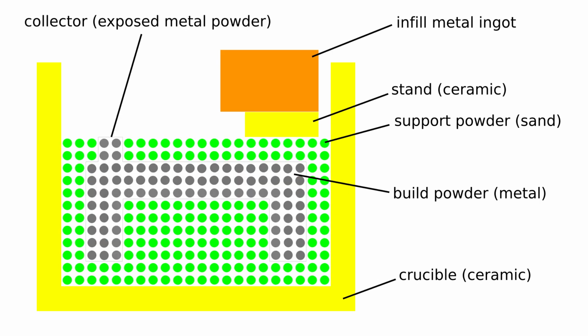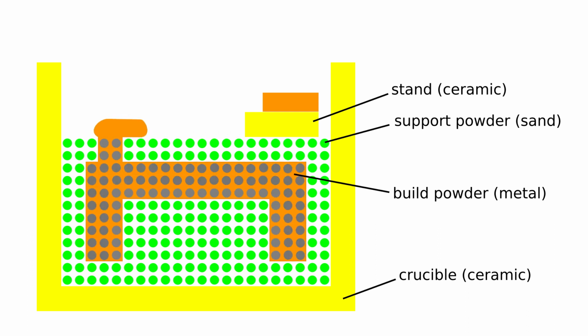In the Puddle+Stand method, we place an ingot on top of a stand, such that the forming puddle doesn't touch it, and we tilt the crucible slightly away from the collector. Because of the tilt, when the ingot starts melting, the puddle of the molten metal will start to form away from the collector. When enough of the ingot melts, the puddle reaches the collector and attaches to it, and absorbs into it completely despite the tilt, again because of the surface tension.